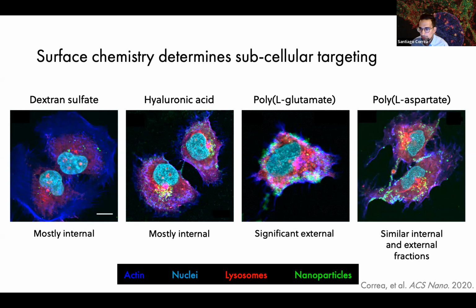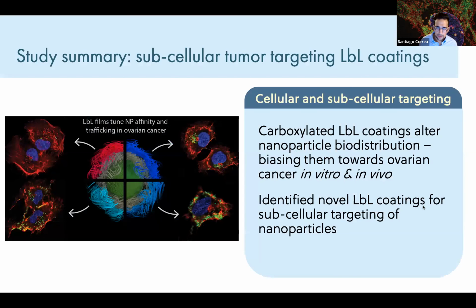And you can see that as this beautiful green nanoparticle signal occurring even on the projections between these two cells. But we're also seeing internalization of the nanoparticle into these lysosomal compartments. And through some additional super resolution microscopy work, we ultimately determined that these polyaspartate particles are being internalized through caveolar mechanisms. And so this study overall revealed some really interesting formulations that we could explore with unique subcellular trafficking properties on top of their ability to home towards these ovarian tumors.